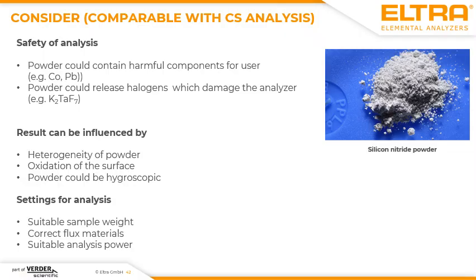The deviation of results, again, can also be caused by the same effects which are relevant for CS analysis, which means heterogeneity of the powder, oxidation of surface, or maybe hygroscopic effects, like in the Elementrac CS-i, and here the effect is even bigger. You also have to consider a suitable sample weight. You have to use here a correct flux for materials, and you have to use a correct analysis power. What this means in detail is discussed in the following.